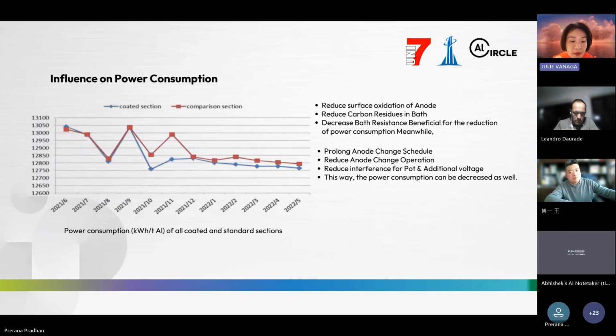On one hand, the protective sintered body reduces anode surface oxidation and carbon residue in the bath, which directly decreases bath resistance and cuts power consumption for electrolysis. On the other hand, the coating prolongs the anode change cycle and reduces the number of anode change operations. So fewer anode changes means less interference to the pot operation, less additional voltage caused by replacement, and a further cut in power consumption. So for smelters, this dual reduction means a lower electricity bill, a smaller carbon footprint, and better compliance with global energy saving and emission reduction regulations. So this is remarkable. Well, let's turn to the next page.